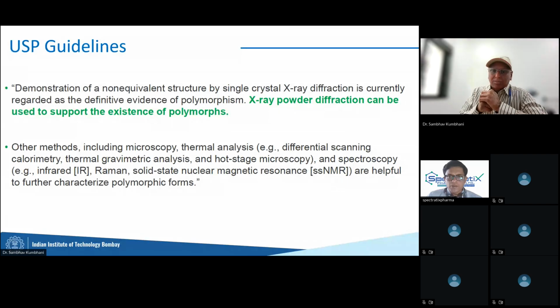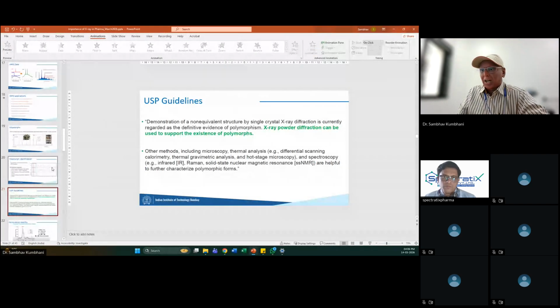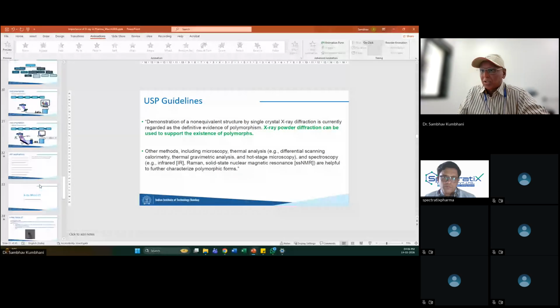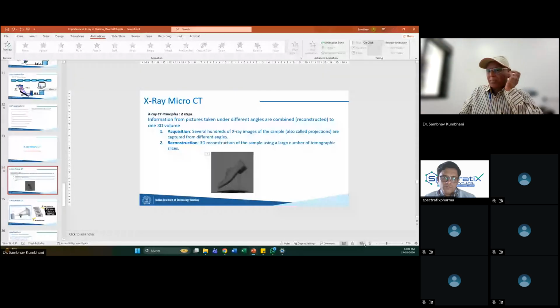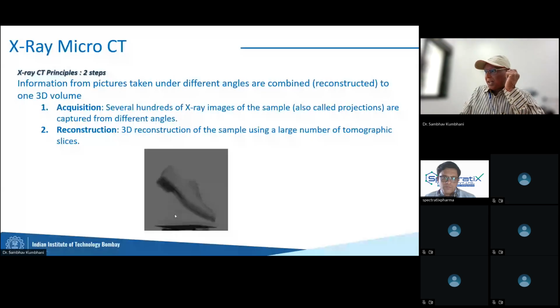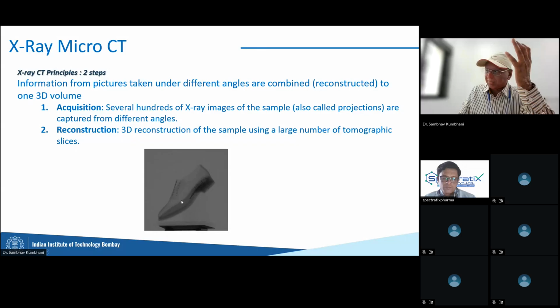So for confirmation, if I have a multi-layer sample, like I just explained, 3-4 layers of coating and then a substrate, I should start with CT. CT will tell me how many layers are present, because each material will have a different absorption or transmission capacity, and will come up as a different shade, which you would have noticed in the image as well. I didn't highlight all that, but it is very obvious. In the shoe itself, the lace is a slightly darker color, the rubber sole is a different color, and the top fabric is a different shade. Really, different gray shades are available on the shoe.